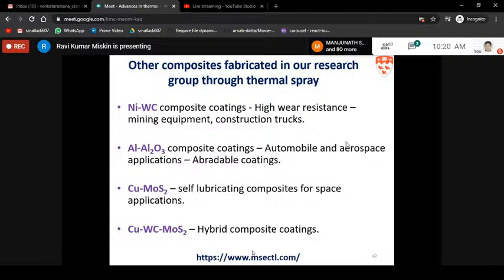And she also studied a hybrid composite, which is copper tungsten carbide MoS2, that is molybdenum disulfide, which actually gave a composite effect, that is, you get both high wear resistance and also low friction. In the case of copper MoS2, there was mostly low friction only. Next.